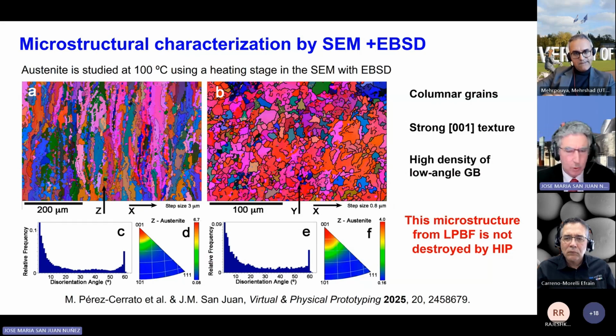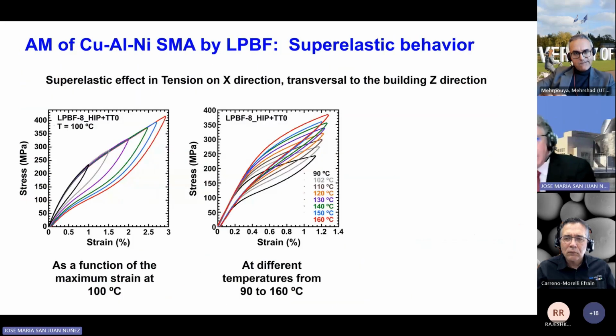Let me move then to the thermomechanical properties. So this is the superelastic effect in tension in the X direction, so transversal to the building direction. And this is at 100 degrees centigrade as a function of the different maximum strain. You can see that up to more than 2.7, we get a good recovery of the superelastic behavior. And this is the same effect at different temperatures.